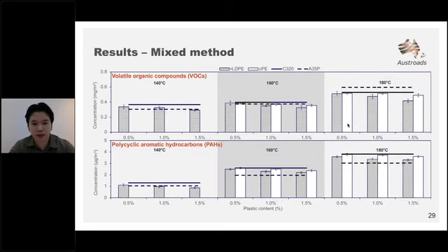Now on to the results. The graphs plotted here show the concentrations of VOCs on the top and PAHs at the bottom against plastic content across all 3 working temperatures. All results are compared to C320 bitumen, represented by the solid black line, and A35P by the dashed line. If you do not already know, C320 is a standard bitumen used in the industry with no content of recycled plastics, while A35P is a commercially available modified bitumen.